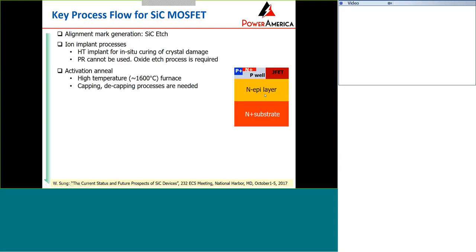I just borrow the process flowchart from Dr. Sung. The process flow for silicon carbide devices starts with alignment marks etched on silicon carbide. The right figure shows the wafer structure. It grows the N-type epi layer of silicon carbide on the silicon carbide substrate. After that, if you make a MOSFET, you need a few ion implantations to implant the P-wells, the source, and the JFET implantations. Normally, most of these implantations require high temperature implantation to reduce the crystal damage, and all these implantations need to be activated at relatively high temperature. So that's a typical process for silicon carbide.